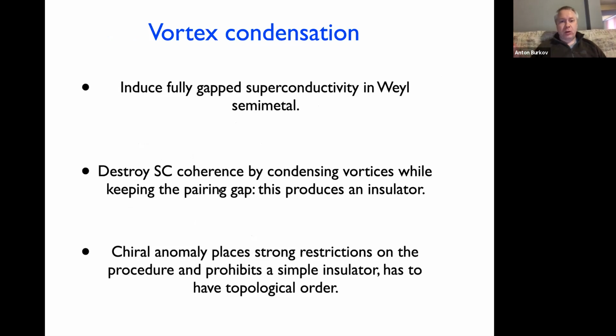Okay, so if I condense vortices in a superconductor, this destroys the superconducting coherence. But since I keep the pairing gap, there are no low energy fermion excitations, and therefore what I get is an insulator. Okay, so what I imagine doing is basically inducing a superconductor to insulator transition in the superconducting Weyl semimetal.